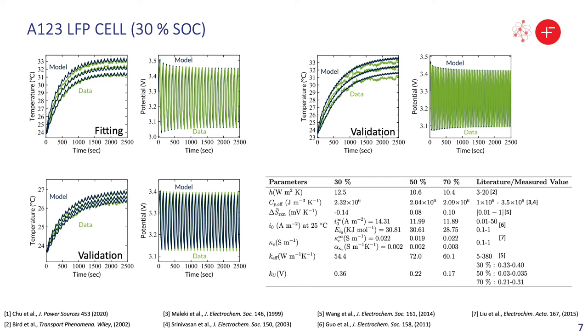The top right shows a 4C 50 second square wave and the bottom left shows a 2C 100 second square wave. Both have reasonable matches and only the operational conditions were adjusted between them.